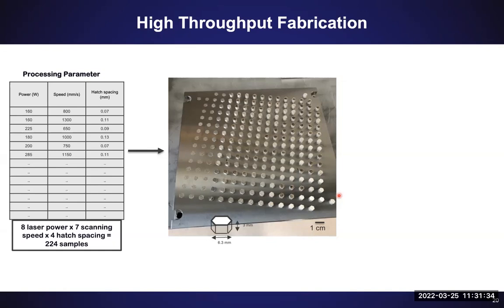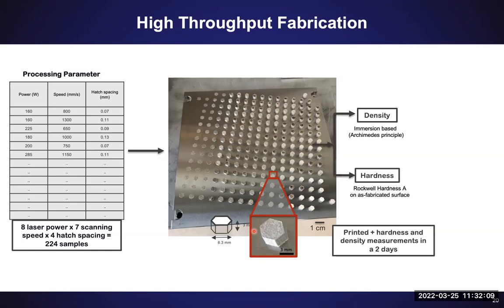and do characterization. So Wisconsin, specifically Dan Thoma, came up with this approach where they were building samples that looked like hex nuts on a substrate plate. The nice thing about this specific shape was that they don't have to send this plate over for machining. They just use a wrench to twist the samples and get them off the plate. I think each plate has about 220 samples where they're looking at 8 different laser powers, 7 scanning speeds, and 4 hatch spacings, so various combinations of those parameters.